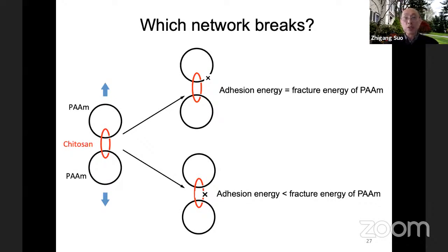The question is: which network breaks? Remember, you have three networks. In our case, there's a polyacrylamide network—this is a pre-prepared network, a very stretchable hydrogel, and another stretchable hydrogel, same. We want to use chitosan to form a third network. So when we peel this and cause breaking, we can ask whether your polyacrylamide breaks, or your chitosan breaks. Experimentally, which thing breaks? And we can see this.